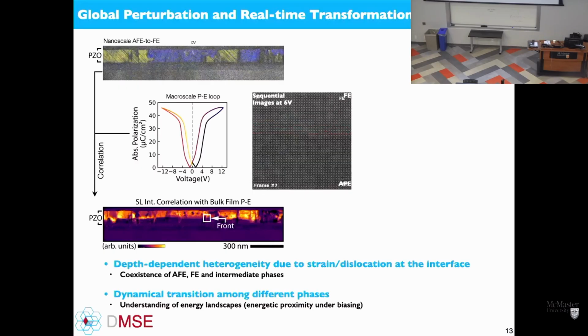And more importantly, we can track this as a function of field. And at a constant voltage of 6 volts, while we're imaging, we'll also notice these boundaries bounce around between the ferroelectric and antiferroelectric, meaning it's at a metastable condition, or it's being stabilized by that applied field. As the electron beam passes by, it applies an electric field that drags that boundary around. And so we can begin to probe sort of the energy stability of the different phases and the boundaries themselves with the electron beam as we're imaging at the applied voltage.